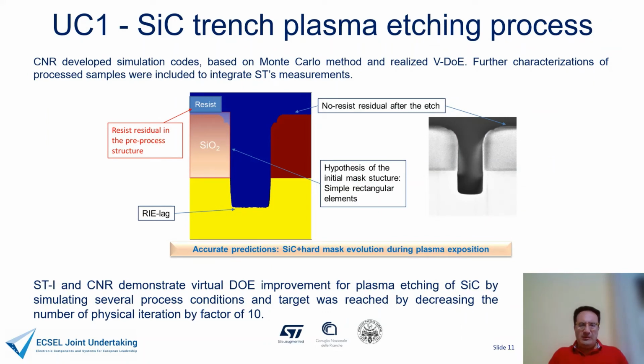When we talk about the first use case, the silicon carbide trench plasma etching process, we got great results in terms of the correspondence between simulation and the real case. We have the opportunity to take into account the full structure, including the photoresist residuals, because the whole structure includes photoresist, the hard mask with silicon dioxide, and the silicon carbide. In this case, it's possible to reproduce at best the structure and the profile that we have at the end.